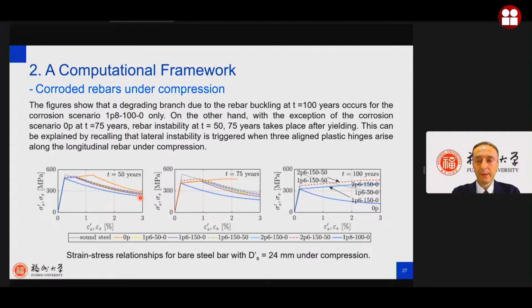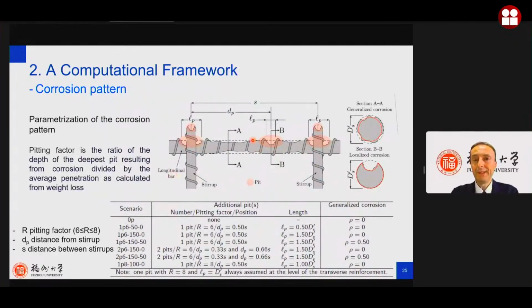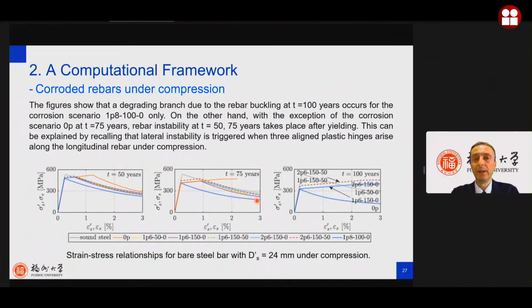consider, the one associated to only one pitting in the middle with a severe pitting factor, so 8, and a dimension of the pitting equal to the diameter of the steel rebars, so the dimension is the length of the pitting, sorry, this one. We obtain that you can have buckling even if you are still in the elastic phase. For all the other cases, you enter first into the nonlinear phase, and after you can have buckling of the longitudinal rebars.